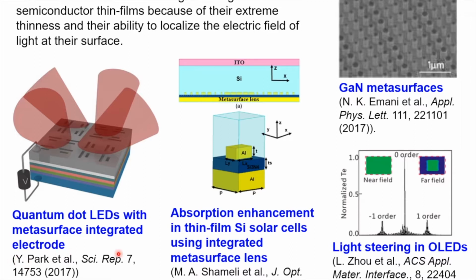In 2017, Park et al. showed that quantum dot LEDs can be integrated with metasurfaces, and it was used essentially for beam steering of the light from the LED. Absorption enhancement in silicon solar cells, thin film silicon solar cells, was also demonstrated by Shameli et al. in 2018, and this was where they integrated a metasurface at the backside of an amorphous silicon solar cell.